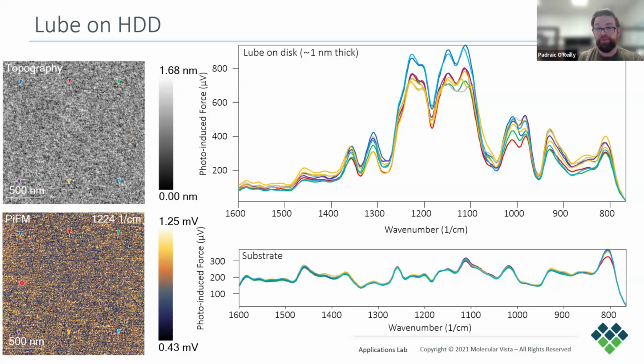The images on the left are taken on the lube sample, and these 6 spectra taken on the surface are shown in the top plot. The bottom spectra are on a bare disk, and you can see that even with this very thin layer, the lube spectra are reproducible and are dominated by peaks between 1100 and 1300 or so.